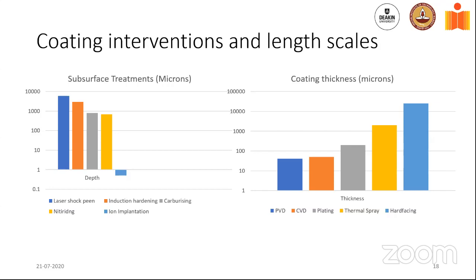And that's what I would do, essentially going from hard facing, thermal spray, plating, CVD, PVD. I think there is some formatting error, but broadly, the hard facing can get you an inch of material on the surface. Thermal spray can get you about 2 to 3 millimeters, about a tenth. But typically, when you're looking at a carbide coating, you're looking at 250 microns, which is around 10 mils.